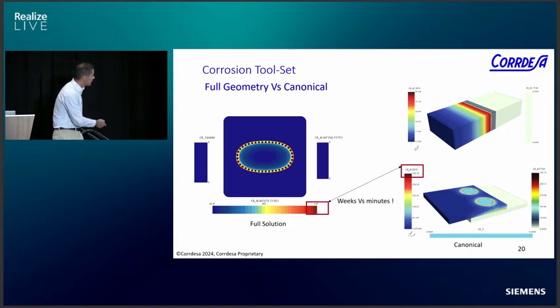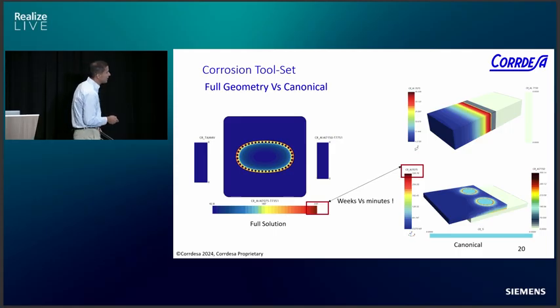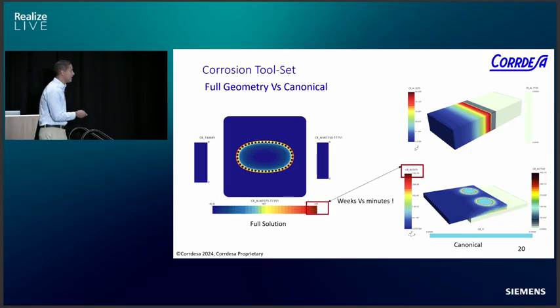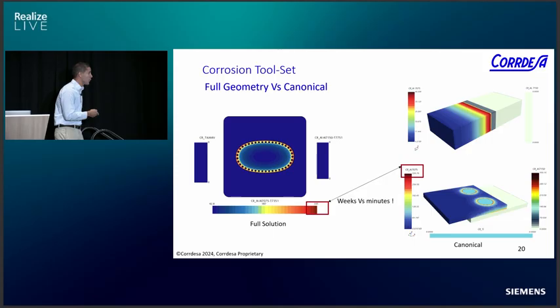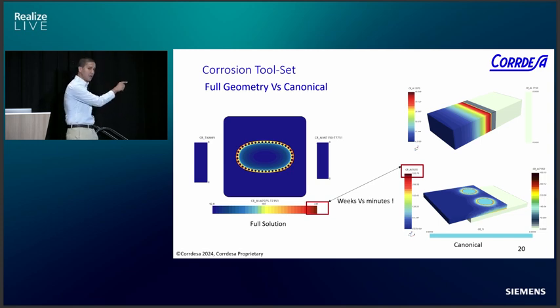We see that the maximum corrosion rate on my aluminum 7075, which is this one over here, is somewhere around 300 microns per year. But my template, that is just a simplification of my model, predicts a corrosion rate of 320. It's absolutely amazing. And this took me more than a week. Pre-processing, meshing, blah, blah, blah. More than a week. And this takes 1 minute. And this is just amazing. That's the reason why folks at the Air Force are so interested in deploying this solution pretty much nationwide.